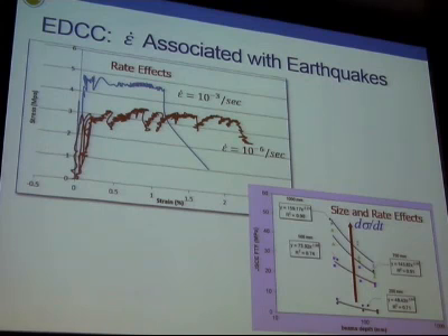Now, when you come to EDCCs, when I'm actually stressing these materials at rates of loading which will be associated with earthquakes, for example, 10 to the power minus 3 per second, that being the strain rate, you'll notice that this is my material under quasi-static conditions, and this is a material under dynamic or earthquake-related conditions. And you will immediately notice that while I do see an increase in strength, as we saw in the previous curves, what I also see is that there is a drop in the strain capacity.